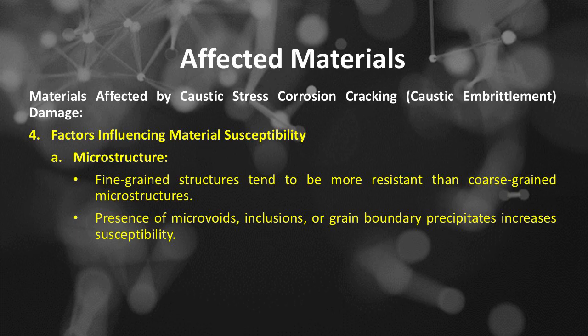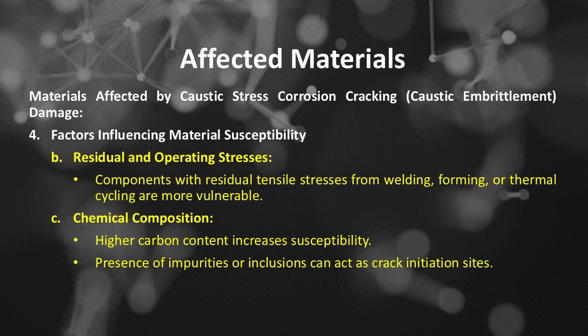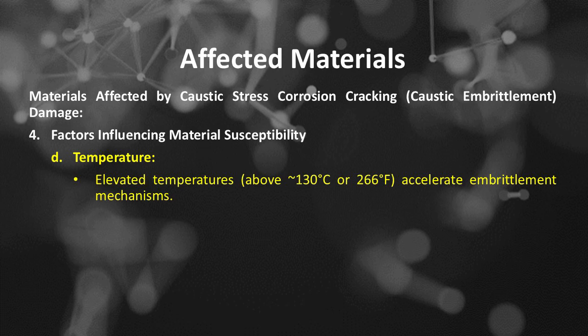Number A, microstructure. Fine-grained structures tend to be more resistant than coarse-grained microstructures. Presence of microvoids, inclusions, or grain boundary precipitates increases susceptibility. Number B of factors influencing material susceptibility. Caustic embrittlement is affected by residual and operating stresses. Components with residual tensile stresses from welding, forming, or thermal cycling are more vulnerable. Number C, chemical composition. Higher carbon content increases susceptibility. Presence of impurities or inclusions can act as crack initiation sites. Number D of factors influencing material susceptibility. Caustic embrittlement is affected by temperature. Elevated temperatures, above 130 degrees Celsius or 266 degrees Fahrenheit, accelerate embrittlement mechanisms.